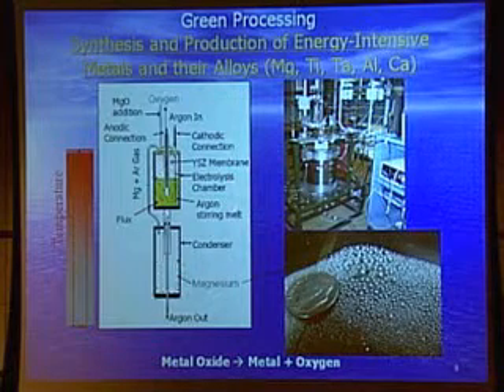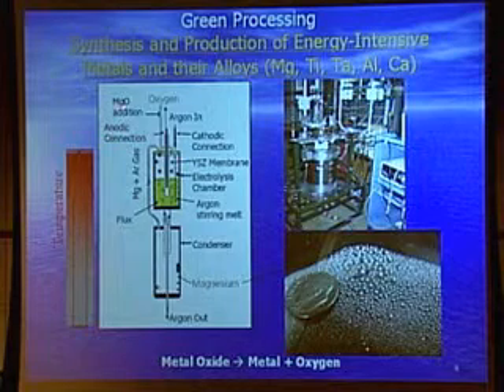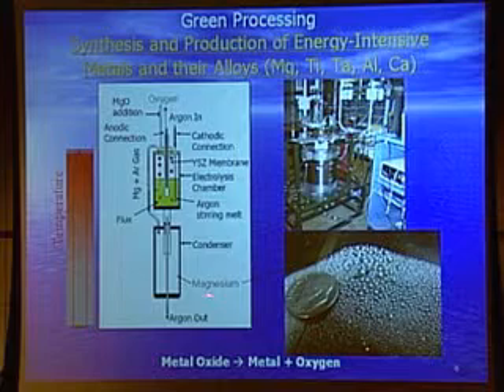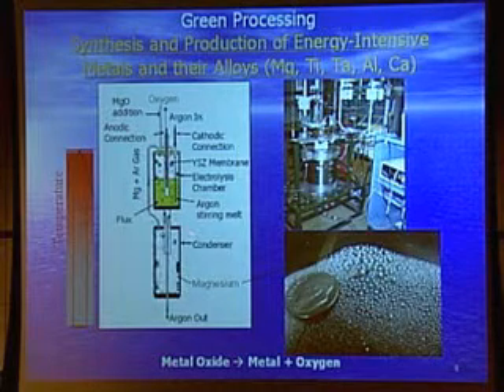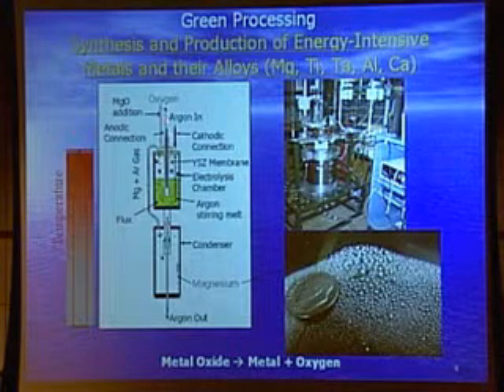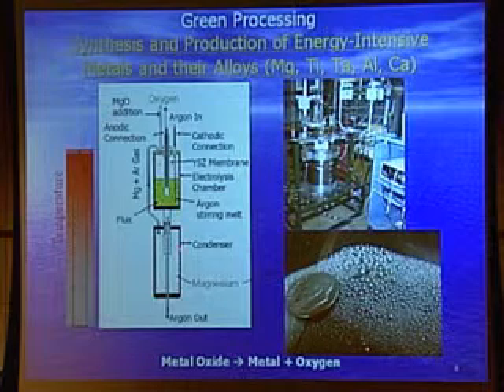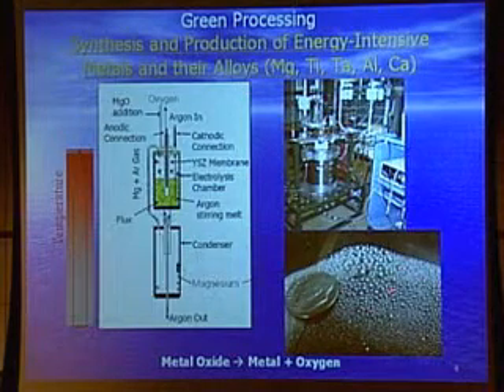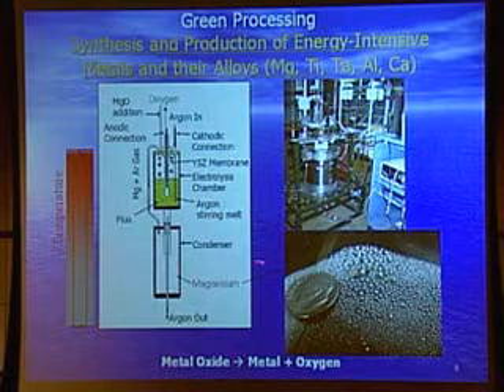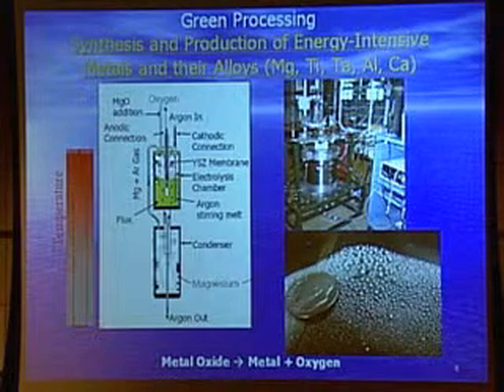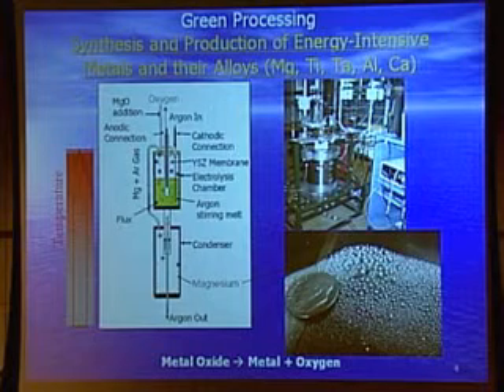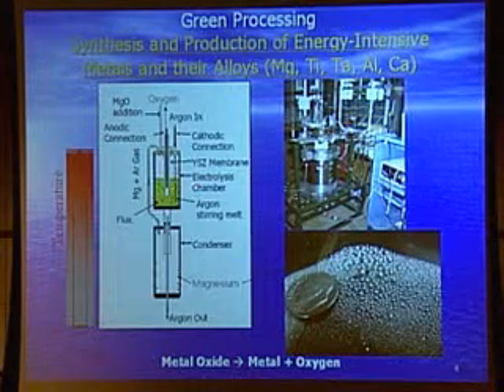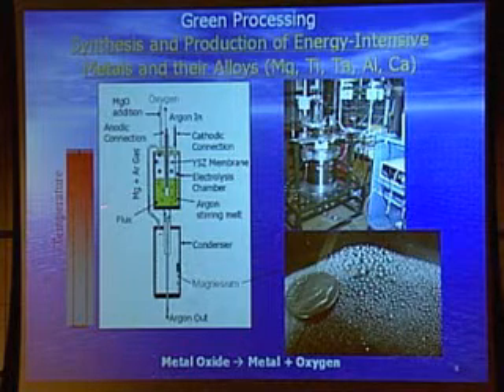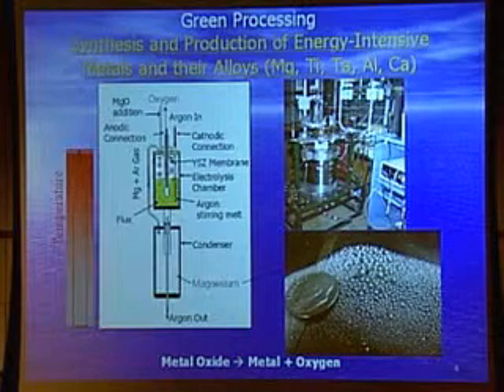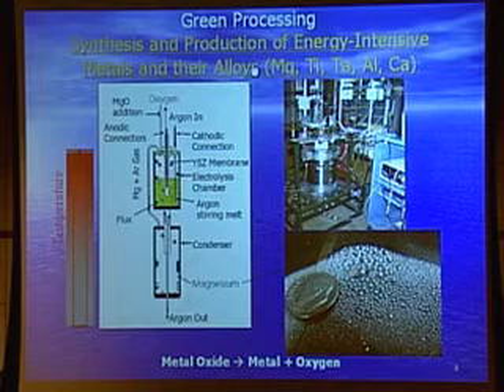Here is a schematic of the setup for the production of magnesium from magnesium oxide. The magnesium oxide is dissociated. We get magnesium metal in the form of a vapor, which is condensed in the reactor, and the byproduct oxygen gas comes out of the solid oxide fuel cell. We can generate this magnesium as very small particles, in fact, we can make nanocrystals of magnesium, which can be used for energy storage applications as well. In this process, the energy consumption is 10 kilowatt per kilogram of magnesium. And if you can scale up, the estimated cost is 30 to 40 cents a pound of magnesium, which is 50% the cost at which magnesium is produced today.